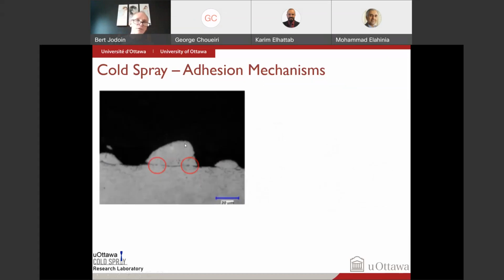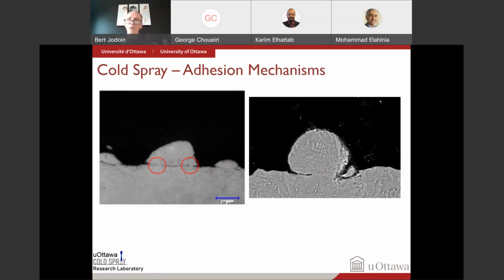Here you get a cross section of one particle on a substrate, and you can see there's a physical link at these locations. You have a gap here for sure, but here you can see a tiny link. So you have metallurgical bonding at these locations. It means this particle was not accelerated fast enough to get full metallurgical bonding, but you start to get metallurgical bonding between the particle and the substrate. That's another example where it might be more obvious. You can see the entire initial particle was spherical. The substrate is here, and you can see a nice metallurgical bonding occurring there. So that's how you get the particles to deform and stick, and you pile them on top of each other, getting cohesion between particles with bonding like this one.